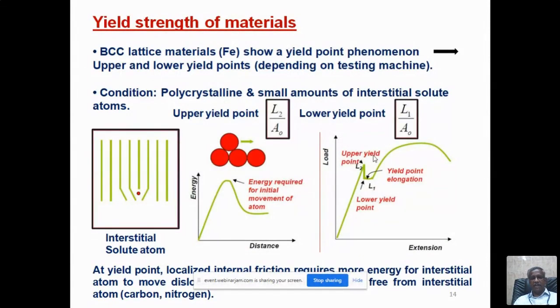The interstitial element means, you see here the red colored balls, these are atoms, iron atoms for example. In between these atoms there is a small gap, among 3 atoms there is a gap. That gap will be occupied by interstitial elements like carbon, boron, nitrogen, oxygen and hydrogen if you add them to that element. These interstitial elements give a pinning effect during deformation, and they raise the yield strength of the material. So if the material contains these interstitial elements, then the yield point phenomenon will occur. What does yield point phenomenon mean?